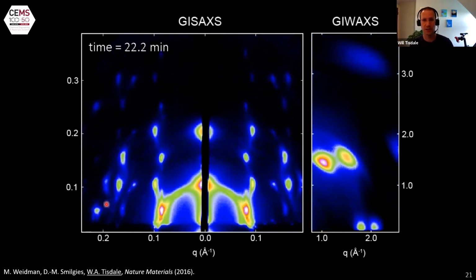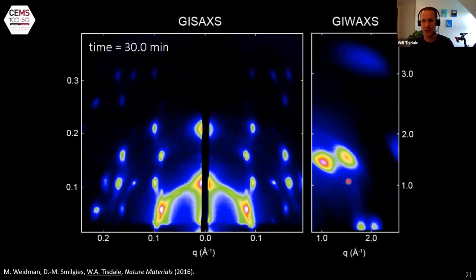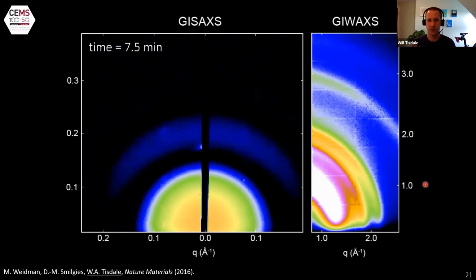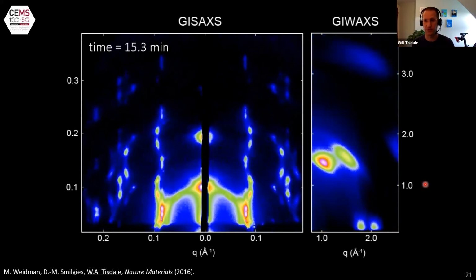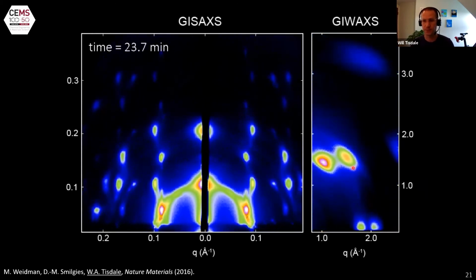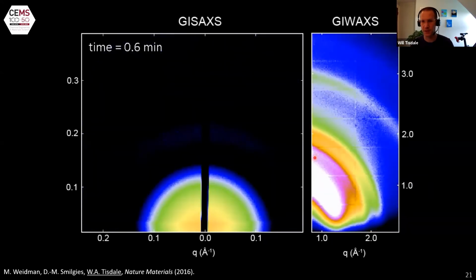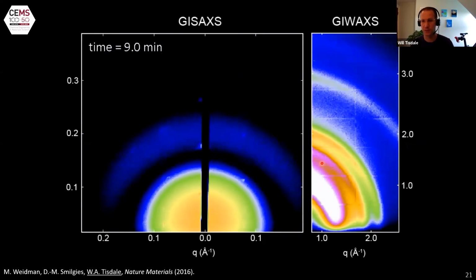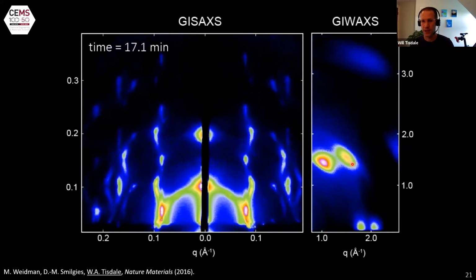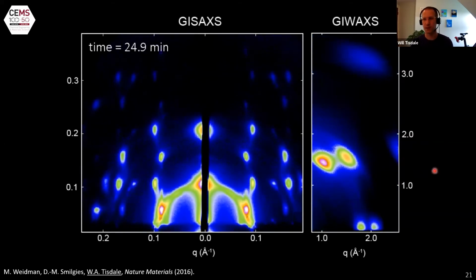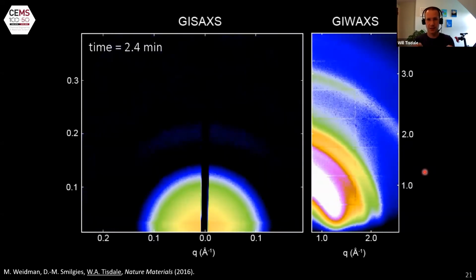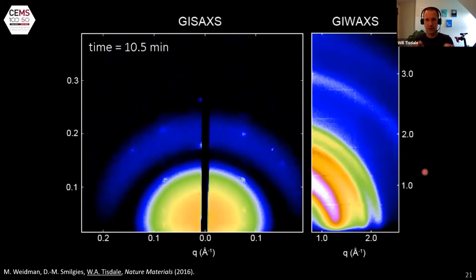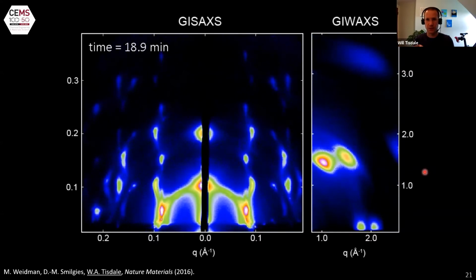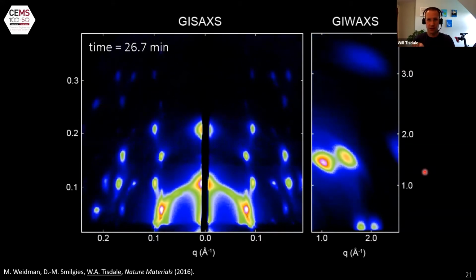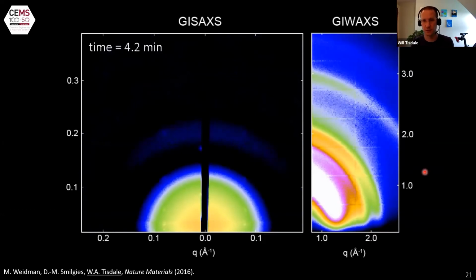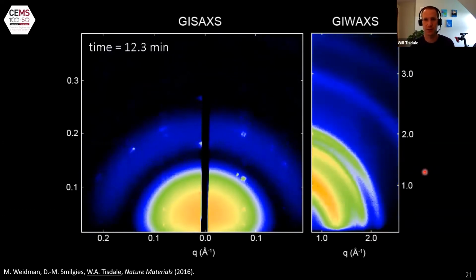Simultaneously, we can coordinate the structure of the superlattice with the atomic scale arrangement of the individual nanocrystals themselves with respect to the laboratory frame through the wide angle X-ray scattering pattern. What's really interesting about this is you'll see that this one wide angle scattering peak forms up nicely while its neighbor continues to evolve. That's telling you that somehow one particular atomic axis of the nanocrystals is well aligned with respect to the laboratory frame, while another axis continues to vary. So there's some sort of coordinated rotation of all of the nanocrystals within the superlattice that's happening during this drying process.